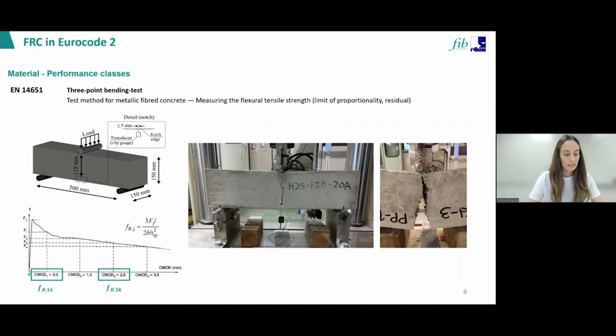Based on this test, the residual flexural tensile strength corresponding to different crack openings can be determined, particularly the characteristic values FR1 and FR3, which are associated with the serviceability and ultimate limit state respectively. It's important to say that this residual strength depends not only on fiber content, but also on parameters such as the fiber orientation, distribution, and also the bond between fiber and matrix.